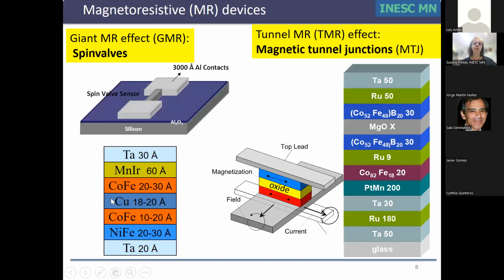So essentially, I'm going to focus on two different families, both very popular. This is a typical structure for GMR, giant magnetoresistive effect devices. It's typically a two-terminal contact with in-plane current. So the current flows in the plane between the two or the four contacts. It is commonly also named a spin valve, a valve that selects the spin. It is a very interesting concept that Bernard Dieny in France introduced. Here internally in my lab, we always use spin valves.